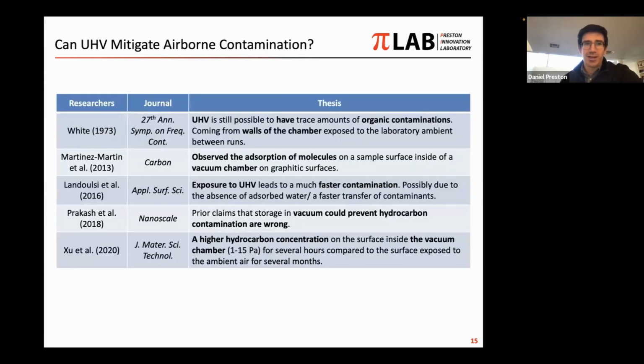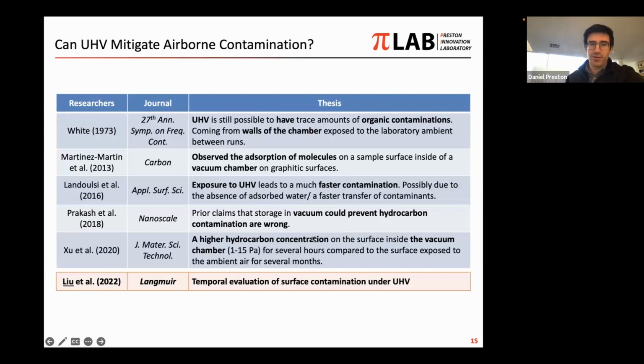And this has been reported, actually, if you really jump in and look at the literature in depth, in a few papers over the years. So exposure to ultra-high vacuums actually can lead to, in fact, faster contamination. And there've been some studies that claim that using the vacuum to prevent the contamination may not be appropriate. And so in our work, which came out last year in Langmuir, we tried to look more quantitatively at this temporal evolution of surface contamination under ultra-high vacuum.